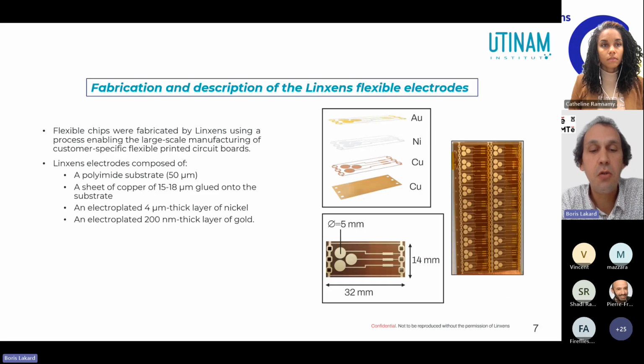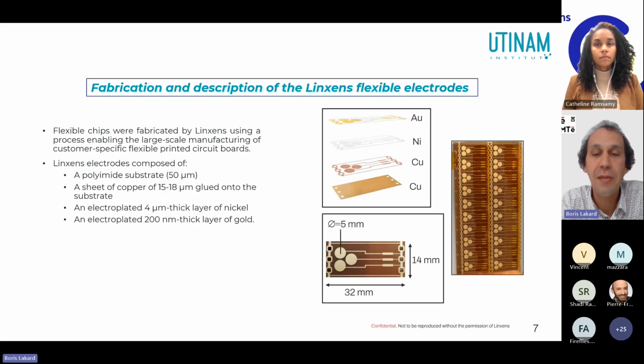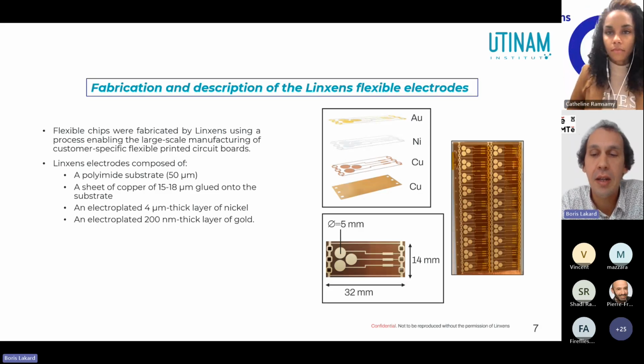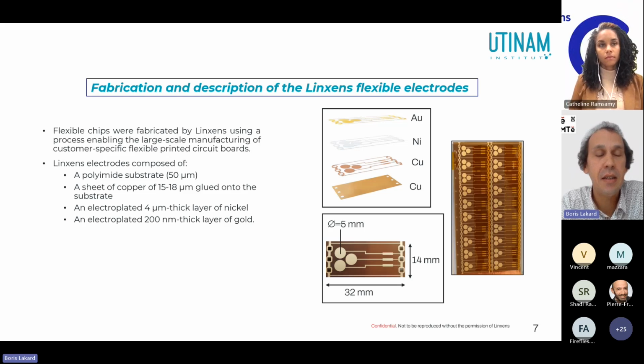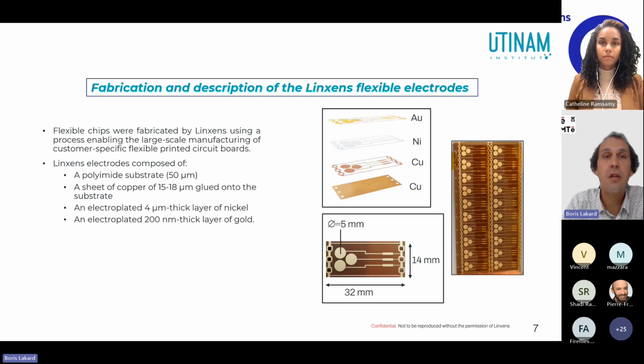For this study, we used the flexible electrodes fabricated using a reel-to-reel process by Linxens. You can see the pictures of these electrodes on the slide. As you can see, these electrodes consist of a polyimide substrate coated with copper foil, then by an electrodeposited nickel layer, and finally by a gold layer on the top of the stack.